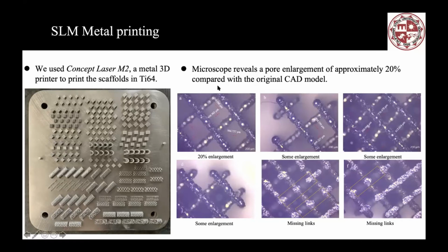But the reason why we picked titanium 64 is we want to invest in titanium's biocompatibility. So, it depends. We printed some samples with stainless steel for a lot of mechanical, functional parts before. From those studies, we thought titanium has better mechanical properties and also better biocompatibility for bone implants, so it would be safer than stainless steel. So we just used titanium for this study. But I know a lot of researchers use stainless steel 316 as well. Thank you.